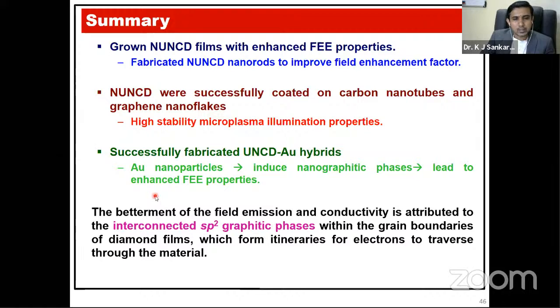So the final thing is that the betterment of the field emission, the microplasma illumination and electrical conductivity is attributed to the incorporation of sp2 graphitic phases within the grain boundaries of diamond films, which forms a very good electron transport within the material and also in the vacuum if you go for one-dimensional materials. So the nanographitic phases in the grain boundaries are the main key factors for the enhancement of the field electron emission properties.